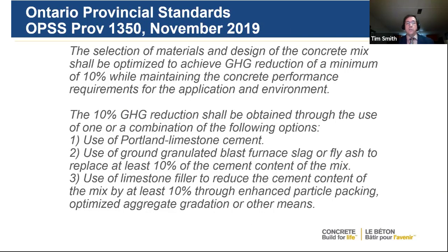The Ministry of Transportation of Ontario, in their OPSS 1350 specification, has specified a global GHG reduction of a minimum of 10%. And they say you can get this through either use of Portland limestone cement, or use of supplementary cementing materials, or the limestone filler. They now allow Portland limestone cement in their specifications, and the Designated Source Materials list for permeability also allows the Portland limestone cement.